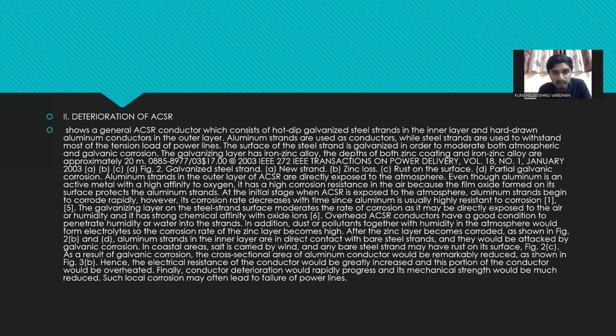On a new galvanized steel strand, zinc loss and rust appear on the surface through galvanic corrosion. Aluminum strands in the outer layer of ACSR are directly exposed to the atmosphere. Even though aluminum is an active metal with a high affinity to oxygen, it has a high corrosion resistance in the air because the oxide film formed on its surface protects the aluminum strands.